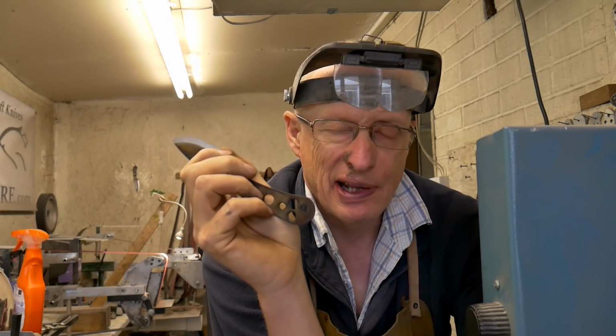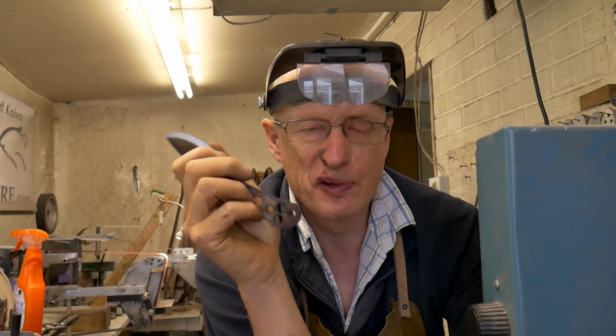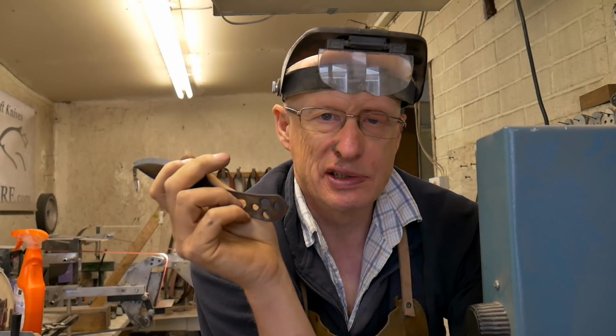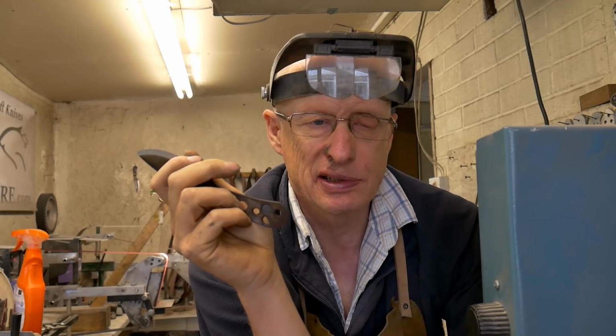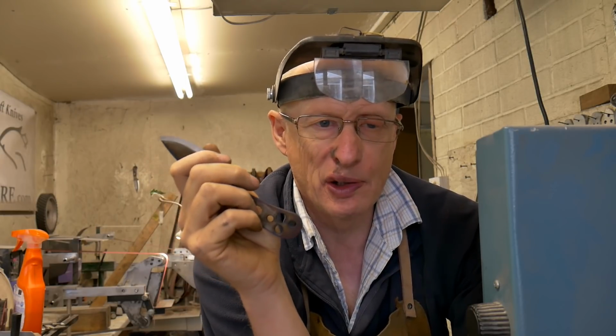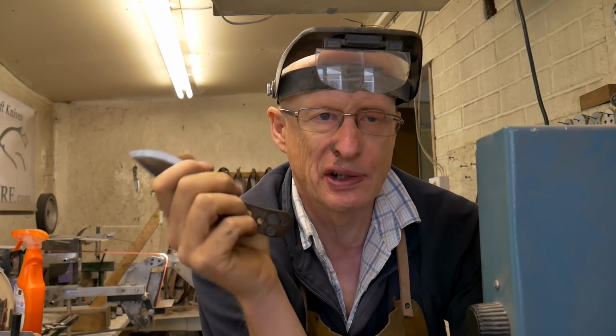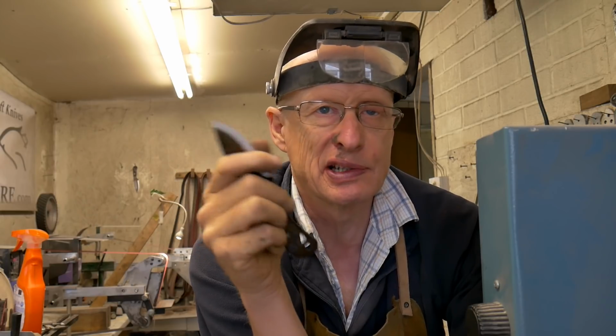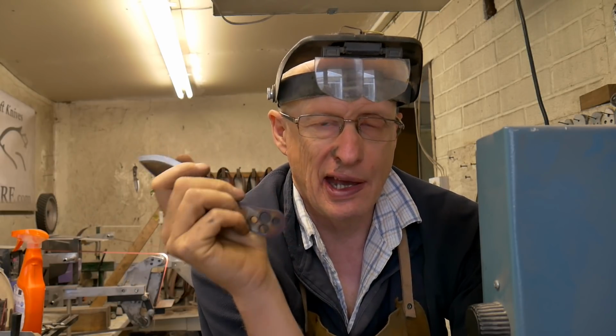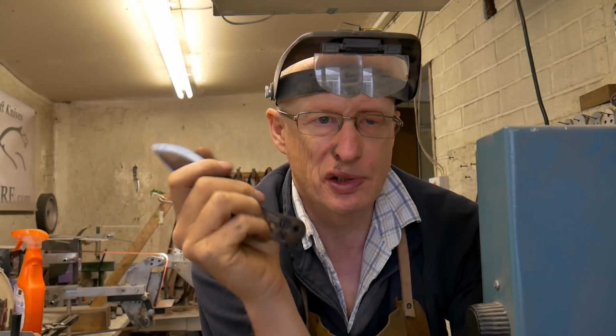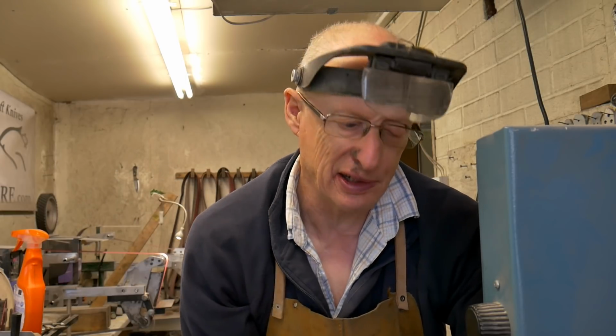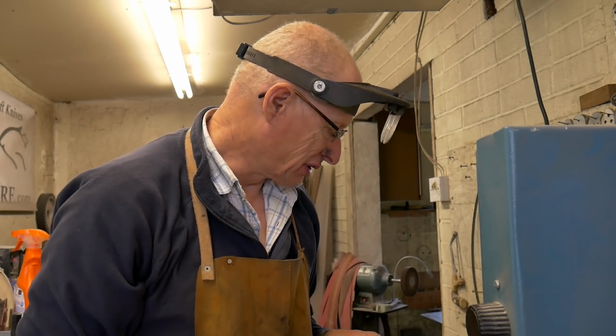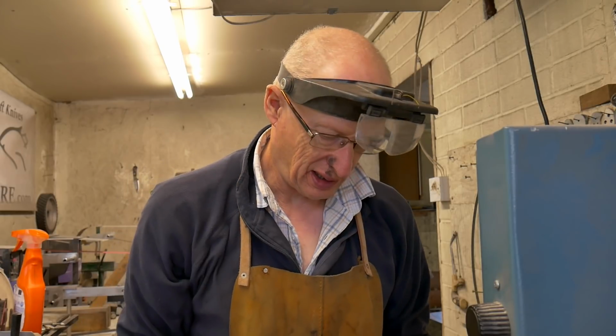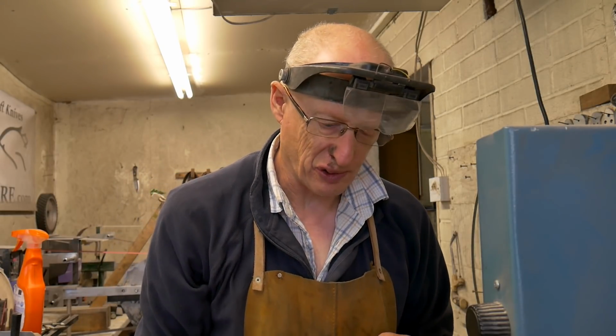Now, every blade, every knife will fail under certain circumstances. It's impossible for it not to fail. If you push it beyond its design, if you push it beyond its limits, the edge will fail, whether it's a good heat treat or a bad heat treat. But it's how it fails which tells us whether we've got a good heat treat or a bad heat treat.